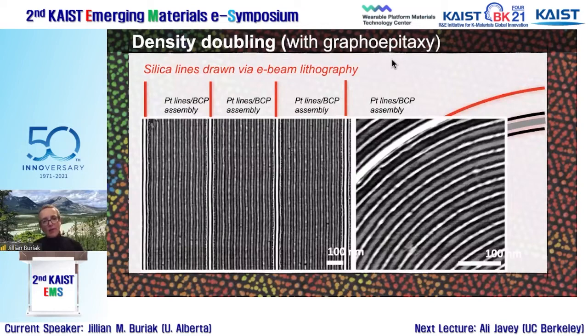It's also compatible with graphoepitaxy. Graphoepitaxy is a horribly fancy word for just saying, I drew some lines, like I took a flat field and I put in curbs so the cars know where to drive. So they have directionality. And in this case, we drew lines of silica on a surface. And when we carry out the block copolymer self-assembly, again, you see that motif of bright, dim, bright, dim that is derived from where the cylinders arose from, whether they're on the top or on the bottom. You can also see it as part of a large circle that we drew. Again, that bright, dim, bright, dim. So yes, you can decrease the spacing by a factor of 2. You can hack it, but it's not perfect.